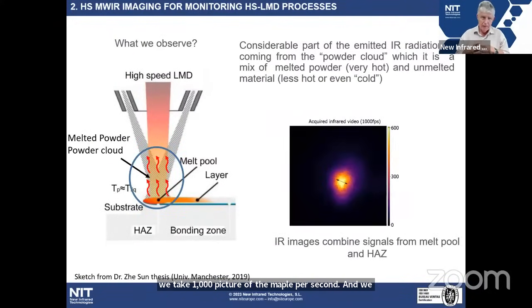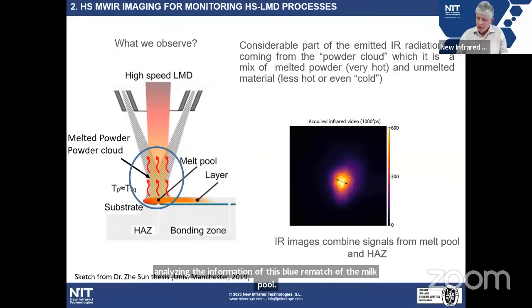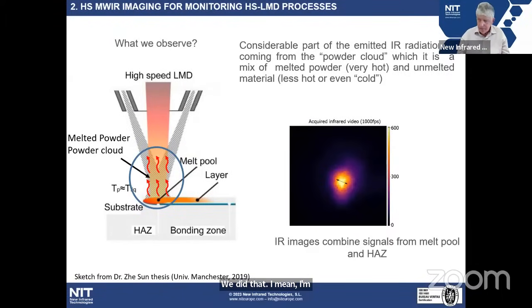But in the case of high-speed LMD, something is different, because the powder is melted above the substrate. As a result, the image we obtain is like a blue melt pool. We have to make an assessment of the process only by analyzing the information in this blue image of the melt pool. And we did that. I'm not going to go into details, but we obtain 1,000 pictures like this per second, and we extract information from them just to be sure whether the process is going well or not.